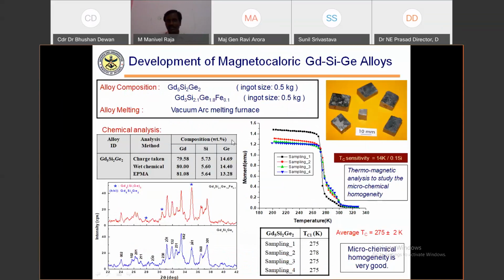These alloys were developed by vacuum arc melting techniques. These are the alloy cut pieces you can see. They were melted by the vacuum arc melting technique. And these materials are operated near the transition temperature so that the maximum change in entropy is observed.